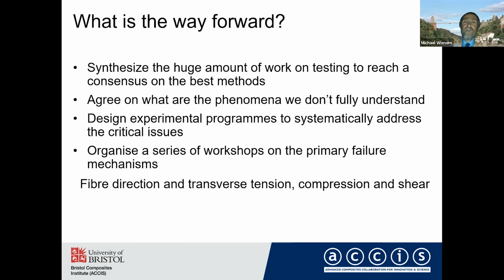Well, of course, those are very good questions. They certainly do have effects, particularly in compression. So I would say that the compression shows more rate and temperature effect. Tensile strength is generally not so affected by those effects because it's fiber dominated, but in compression in particular, I guess the hot-wet is usually the worst one for compression because you get a lot of degradation in the matrix support in those conditions. So that's definitely very important.